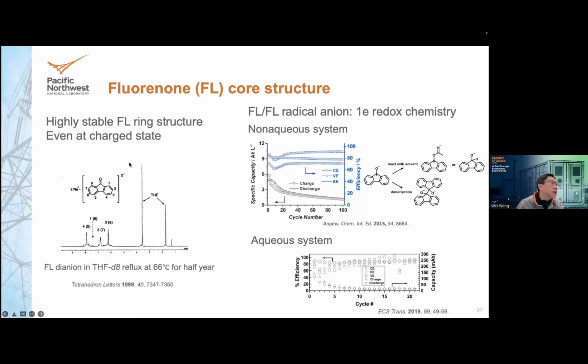So the fluorenone, this material, we know that it's very stable. This is a previous study of this material refluxed at elevated temperature for more than half a year, and the before and after spectra show that the structure is not degrading. But this material has an issue: it is not reversible. You cannot put it in the battery.